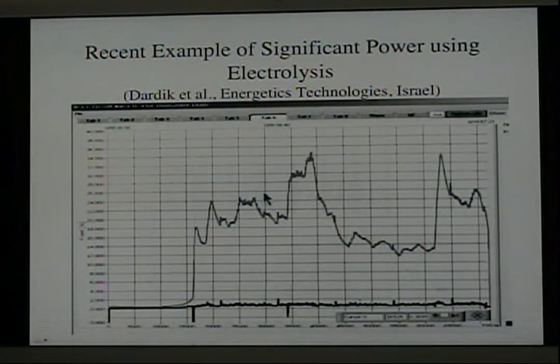Here's a recent result reported by a company in Israel. This is an electrolytic study using palladium as the cathode, heavy water as the electrolyte. For a period of time while the cathode material was being loaded or reacted with deuterium, no excess heat was found. And here a little bit of excess heat was seen. The power was increased, but not in excess of 1 watt. So we're looking at a very small amount of input power. But at the same time, the amount of excess power on this axis increased dramatically, reaching an amount of 34 watts. This is rather erratic and unstable power that's being produced, but nevertheless it is significantly in excess of the error in the calorimeter.